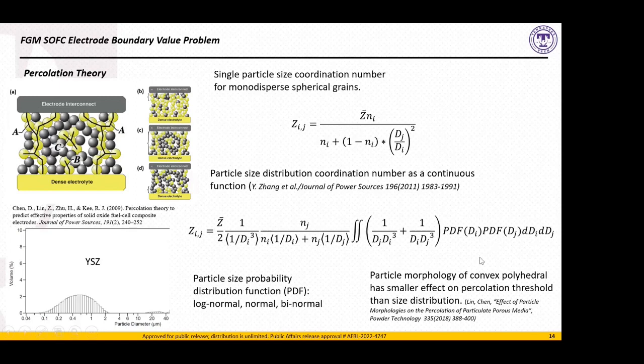We also, again, notice that Lin showed in 2018 that particle morphology has a smaller effect on the percolation threshold than the size distribution. So particle morphology can refer to grains that are more of a cuboid or a tetrahedron or something like that, as opposed to a sphere. But many of these percolation thresholds, the patterns and the functions, are going to be somewhat similar. Now, again, we are assuming here a log normal distribution.